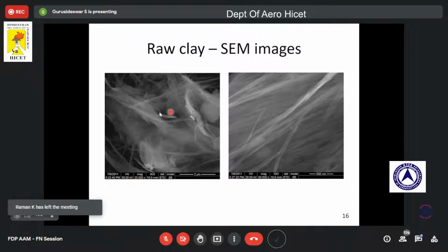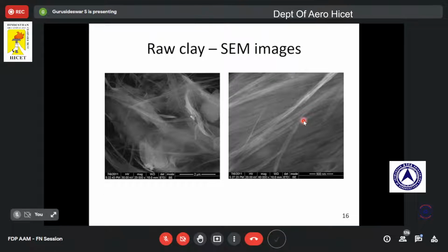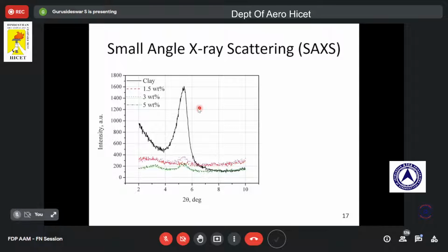You can see it is an agglomerated state, wherein the right hand side shows higher magnification of nano clay, around 60,000x. So this was taken using scanning electron microscopy. And also we have done the small angle X-ray scattering.